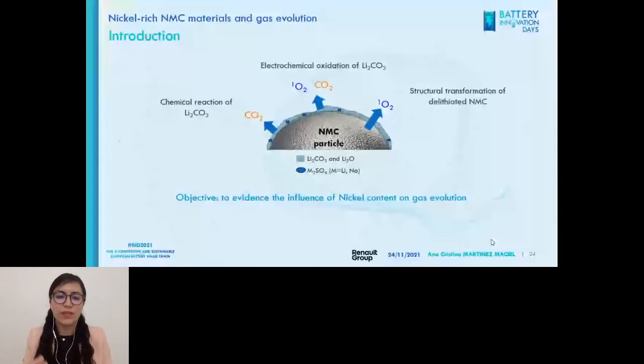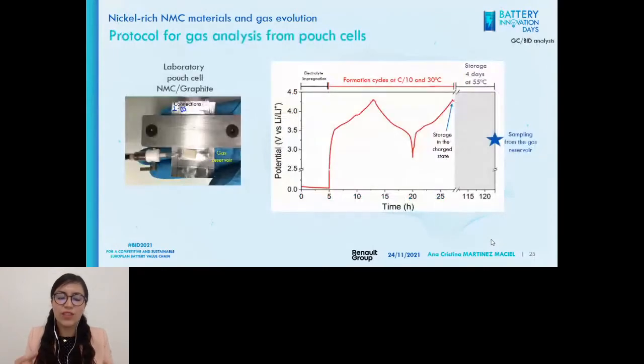So the objective of this part was to evidence the influence of the nickel content, because we are talking about high nickel, nickel-rich materials, on gas evolution. For this, we used laboratory scale pouch cells. We did NMC, either 622 or 811, I will show you when they come. And we implemented a septum through which we could extract the gas safely.